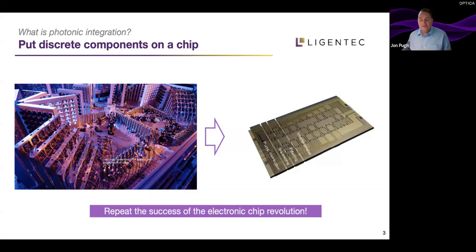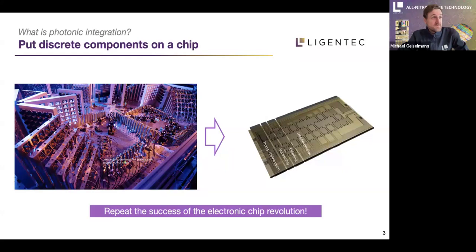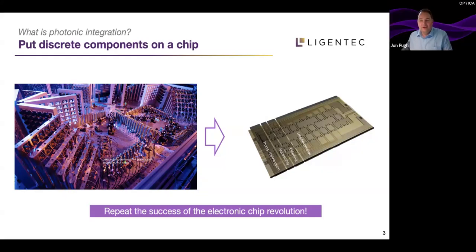Great. So York is asking, how much additional space is required on the chip for enlarging the mode field diameter from the 1 micron to the 9 microns at the edge coupler? Roughly, I guess, hundreds of microns. So it's quite large, and obviously this would be smaller if you're only required to go up to 3 microns, for example.